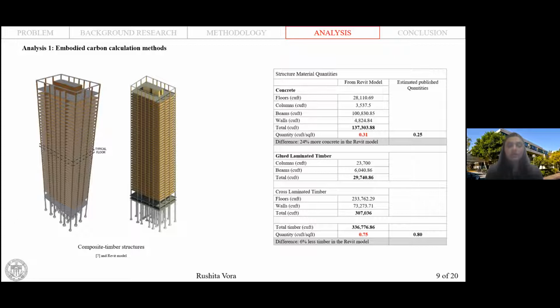in the report. While doing so, a small discrepancy was noted in the concrete quantity, wherein the concrete was almost 24% higher in the Revit model. This was attributed to the fact that the concrete sections in the Revit model did not have RCC modeled into them due to lack of available data, as a result of which the overall volume of concrete increased.